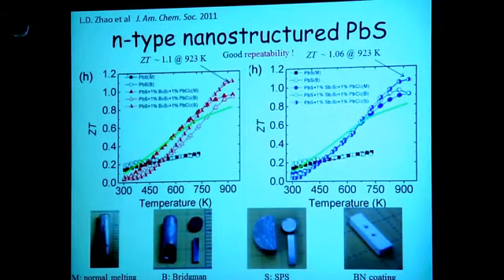So then, because there was no sign of saturation, we deliberately got data up to 900 Kelvin. And you see, with specimens that are shown here that were spark plasma sintered, we were able to get data that exceed 1. And this is remarkable for something like lead sulfide. Exceed 1.1 for the bismuth case, about 1.06 for the antimony case.